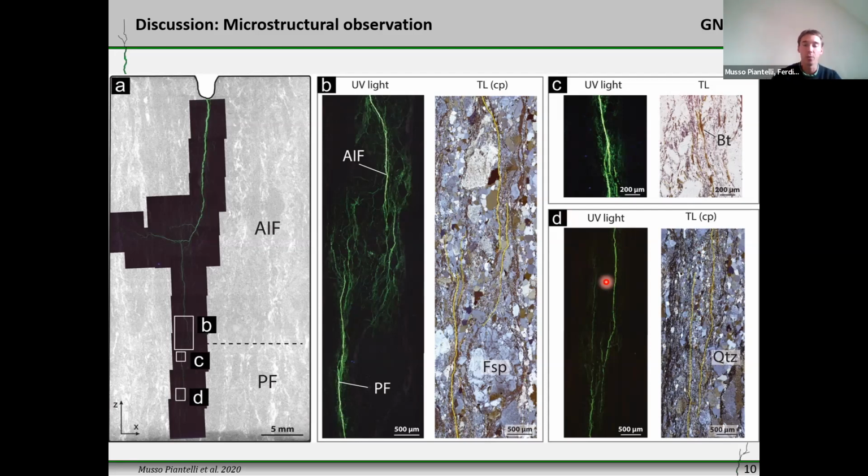to propagate through them. Whereas as soon as the fracture encountered feldspar porphyroclasts, for example, or larger quartz grains, the stress to be accumulated at the fracture tip before it could overcome and jump to the next weakness was a bit larger, and therefore probably the fracture in these kinds of zones had to halt, and then when enough stress was accumulated, jump to the next weakness.